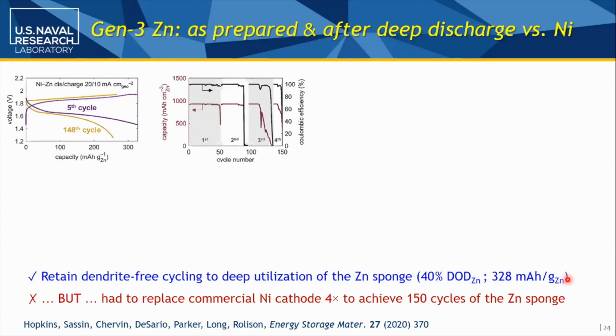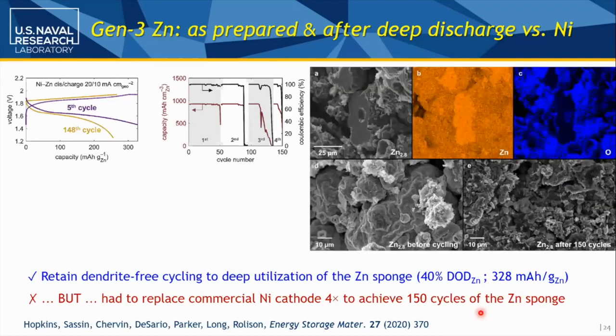He put it versus a harvested nickel cathode in our coin cells. And he had designed his coin cell so that he could remove the cathode part without really disrupting the separators or the zinc and replace the cathode, which he had to do because when he started to see any fade, he put in a fresh nickel cathode and it would kick right back up. So he did that 4 times. He was doing 40% of all the zinc being oxidized and recovered during the charge cycle. And it got to 150 cycles, but he had to replace that cathode 4 times. Whereas the zinc was just doing backstrokes because it's saying, you know, throw a better cathode at me.